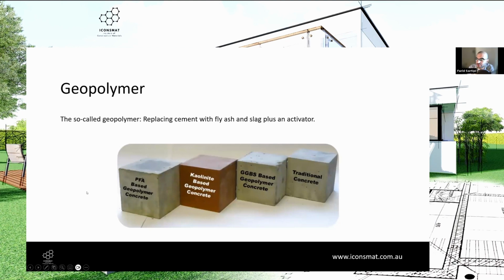There's something called geopolymer concrete, which is concrete without cement, in other words. So we're replacing cement by fly ash and slag, plus something called activator, which is normally sodium hydroxide, and a concrete block is made without having cement. So by replacing cement with fly ash and slag, which are waste materials from other industries, we can reduce the